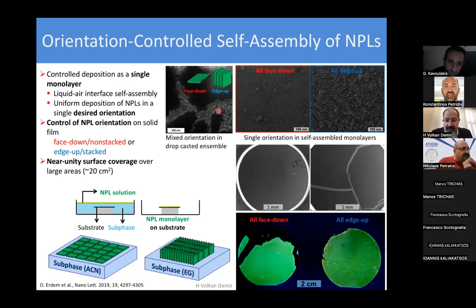You would have face down, edge up, and this is what it would look like on a TEM grid. You can see the edge up from the side, quite stacked like this in a chain structure. You can also see here, as I show with my pointer, the individual face down orientation. We'd like to have either, and this is the approach we developed using subphase. This is actually interface of liquid with air. This type of technique is well known for a large variety of organic molecules and other type of inorganic, organic nanoparticle systems. And here we have to develop this particularly for the colloidal quantum wells.